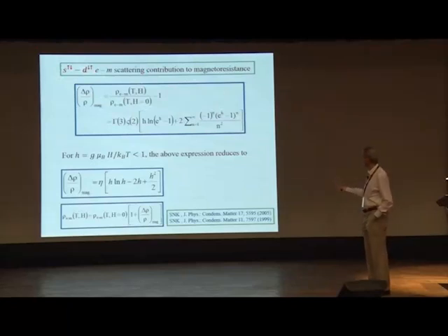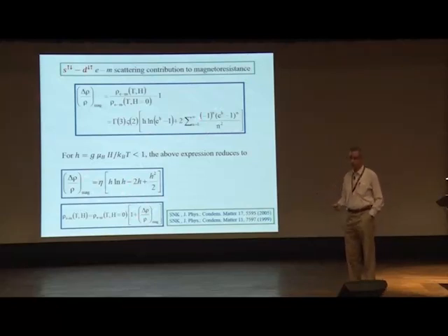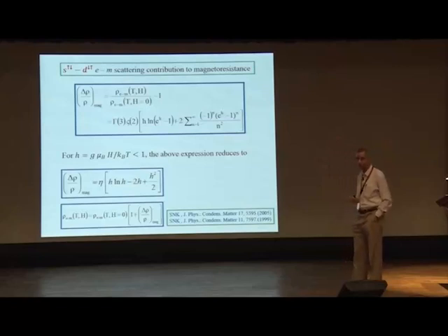Now, this is what theory would give you. And you can relate it; there are various ways of doing it. For magnetoresistance, either you can measure the isotherms, like magnetoresistance versus field at different temperatures, or magnetoresistance versus temperature at different fixed fields. So what we did was measure magnetoresistance as a function of temperature at different fields, because we were measuring resistivity in zero field and at different field values, right up to 9 Tesla. So we could get both of them; you can reconstruct one from the other.